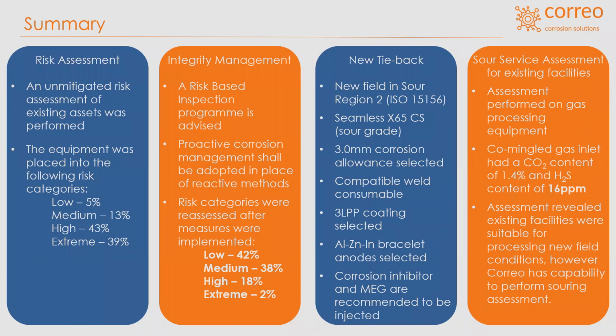So for the new tieback, the new field in sour region 2 based on ISO 15156, we have a few recommendations here: having a seamless X65 carbon steel sour grade and 3 mm corrosion allowance selected, and we need to have compatible weld consumables, and the coatings selected, like 3LPP. And regarding the bracelets, aluminum, zinc, indium anodes need to be selected. And for corrosion inhibitors, MEG is recommended.